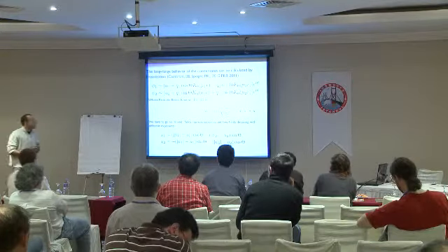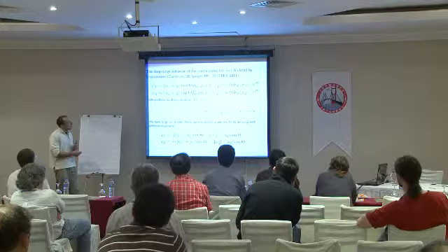But it does one radical change also, in addition to this step. If you now take your original condensates and calculate the asymptotics away from the vortex core, then if you do a careful calculation, you will find that the asymptotics of field 1 and field 2 will be the same at very long distances, no matter how small your Josephson coupling is.